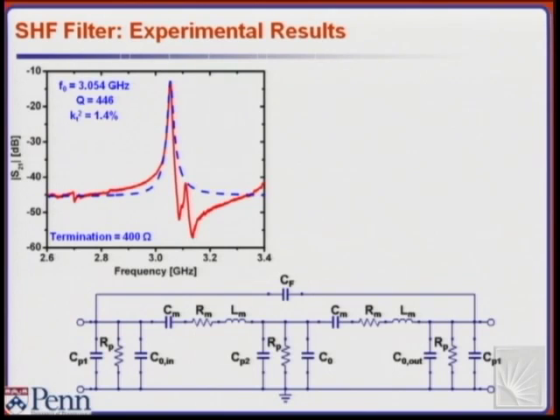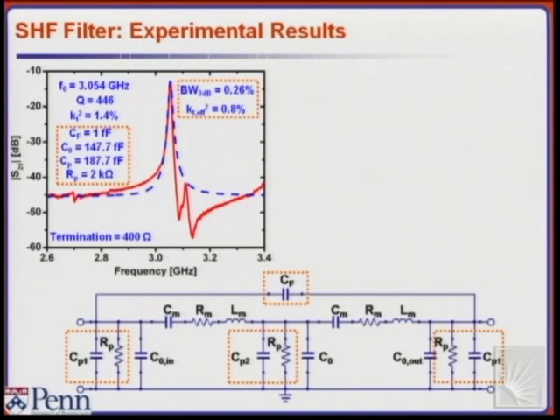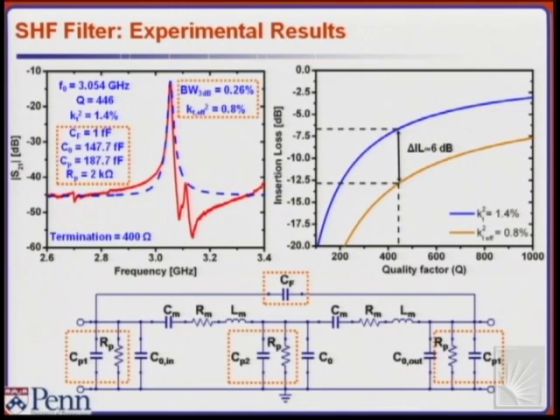Yes, you have some sort of a filter response, and you have small impedances and everything, but your insertion losses are really the key problem, and they are affected. Here we get about 11 dB of insertion loss, which is relatively large for a filter of that frequency. But you can see how much that's affected by the parasitics. So if you design around the parasitics, either by directly integrating with CMOS or by redesigning the capacitance of your device, you could design the capacitance bigger than the parasitic capacitance. With the same device, if you were to remove those parasitics, your insertion loss would go down to about 6 dB, which still wouldn't make it the best filter available.